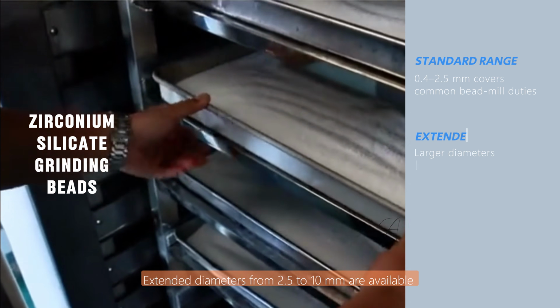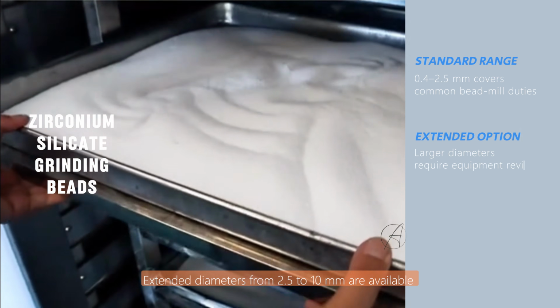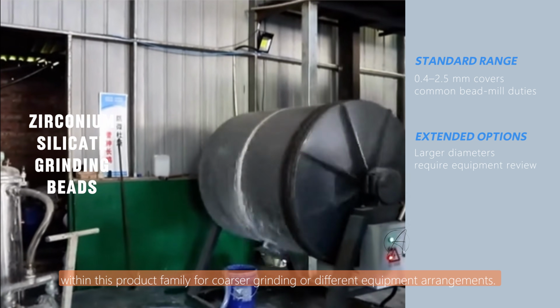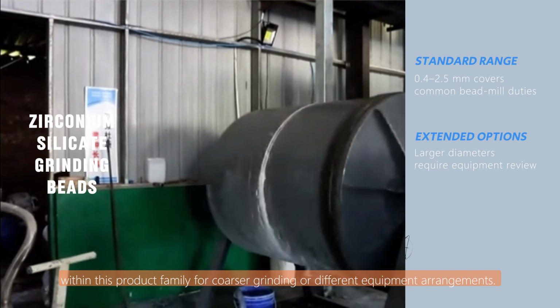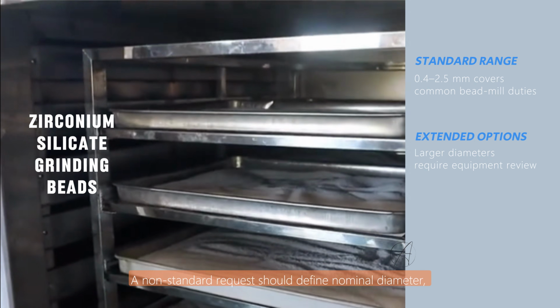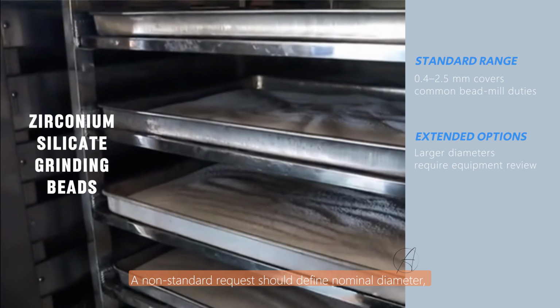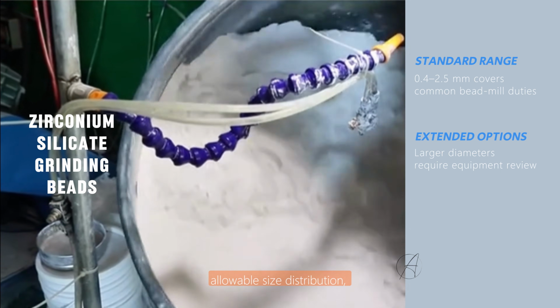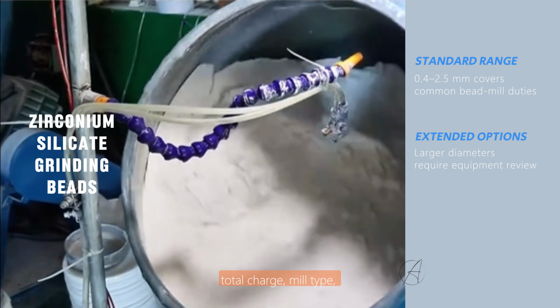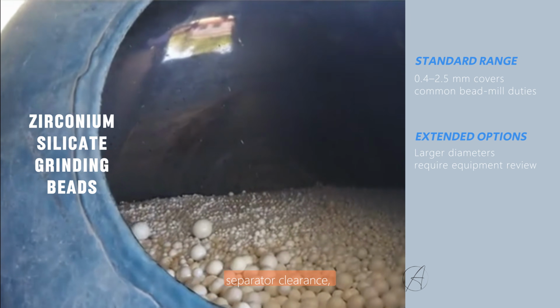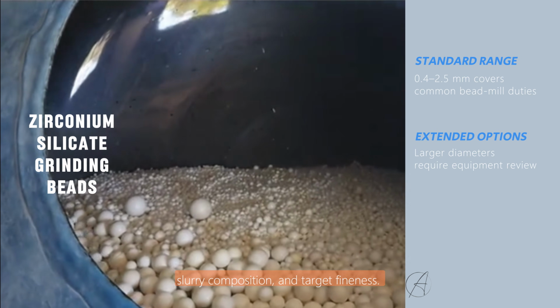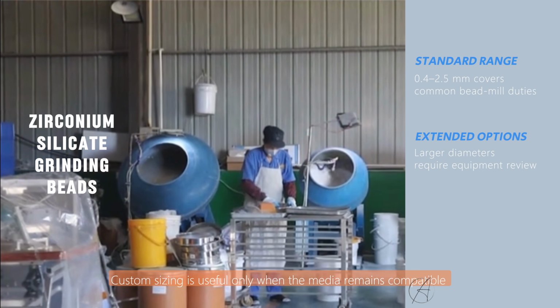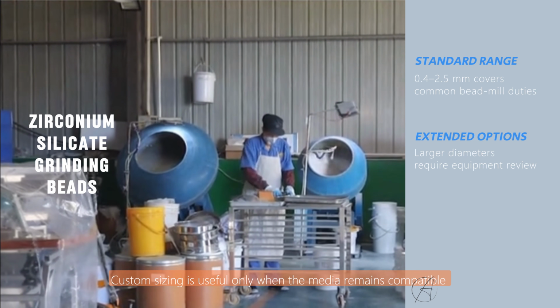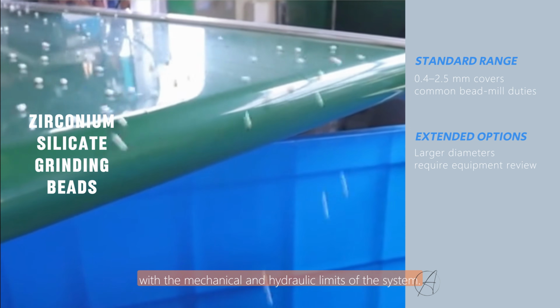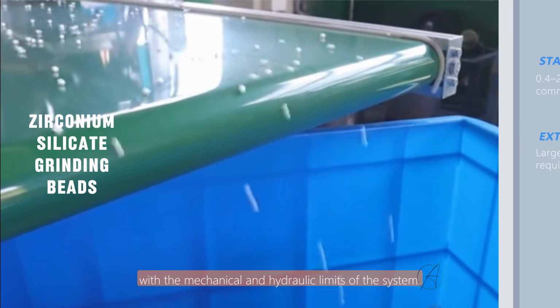Extended diameters from 2.5 to 10 mm are available within this product family for coarser grinding or different equipment arrangements. A non-standard request should define nominal diameter, allowable size distribution, total charge, mill type, separator clearance, slurry composition, and target fineness. Custom sizing is useful only when the media remains compatible with the mechanical and hydraulic limits of the system.